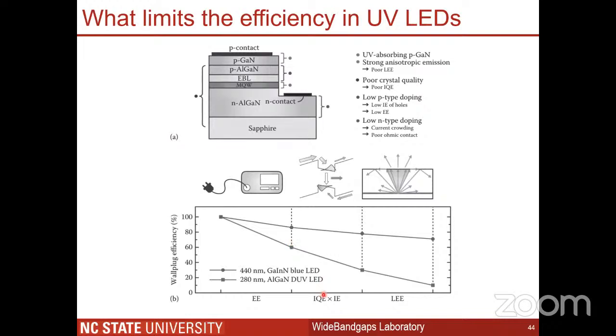Then we talked about internal quantum efficiency, and that depends on the defects in the multi-quantum well, which is the active region in these LEDs. And these can be very low if you have a lot of defects in the material. Blue LEDs magically work very well despite having a lot of dislocations, but AlGaN LEDs do not work well with dislocations. So the internal quantum efficiency is low for these, and that's why the graph goes down further to about 40%.